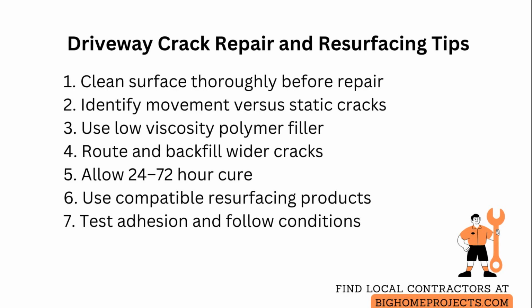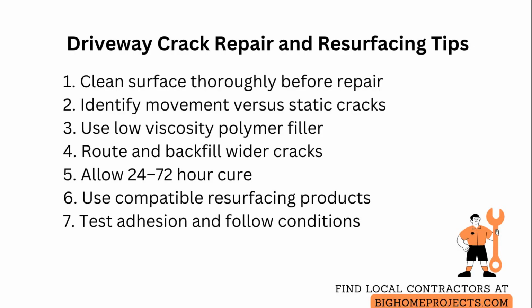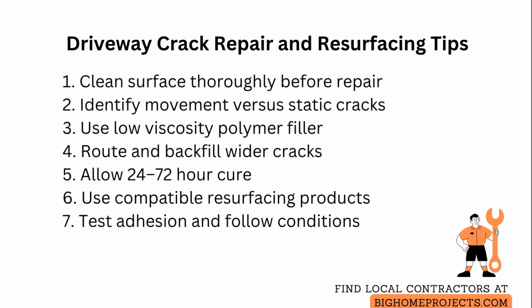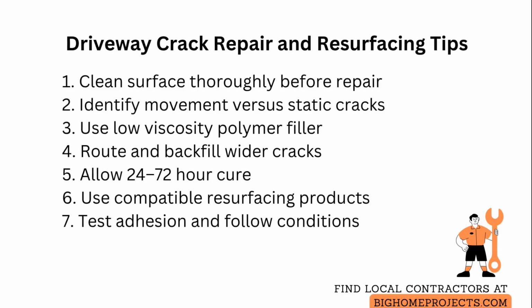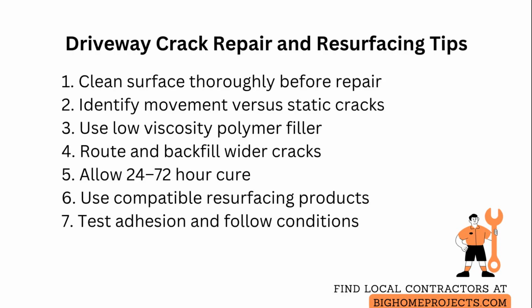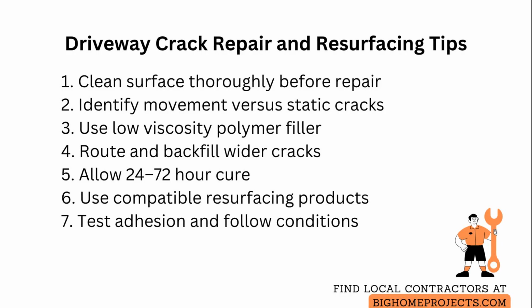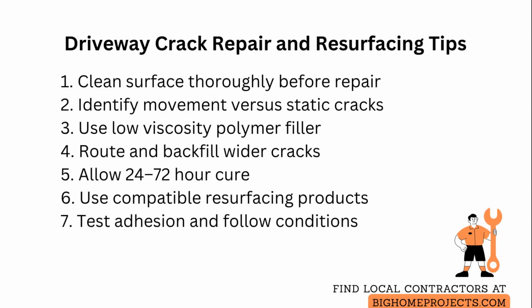For hairline and small cracks, use a low viscosity, polymer modified crack filler applied by pour or gun to penetrate the void and bond to the sides. And for wider cracks, route to a uniform trapezoid and backfill with a hot pour or high modulus sealant to prevent water intrusion. After filling, allow the recommended cure time, which is often 24 to 72 hours depending on temperature